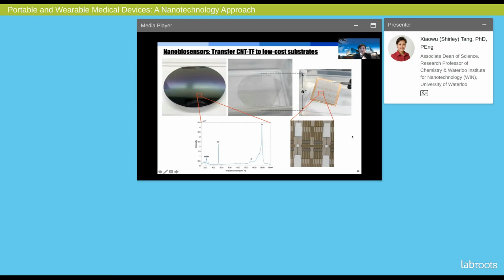Here shows the transfer process. On the upper left corner, it's a 6-inch wafer with a carbon nanotube thin film already grown on it. Raman spectroscopy was used to examine the quality. The peak over here indicates high-purity carbon nanotube on the silicon substrate. By the transfer process we have, this thin film can be lifted and then deposited as a whole onto a plastic substrate with patterned gold electrodes. And therefore, each wafer of thin film can be made into an array of 50 to 200 sensor devices.